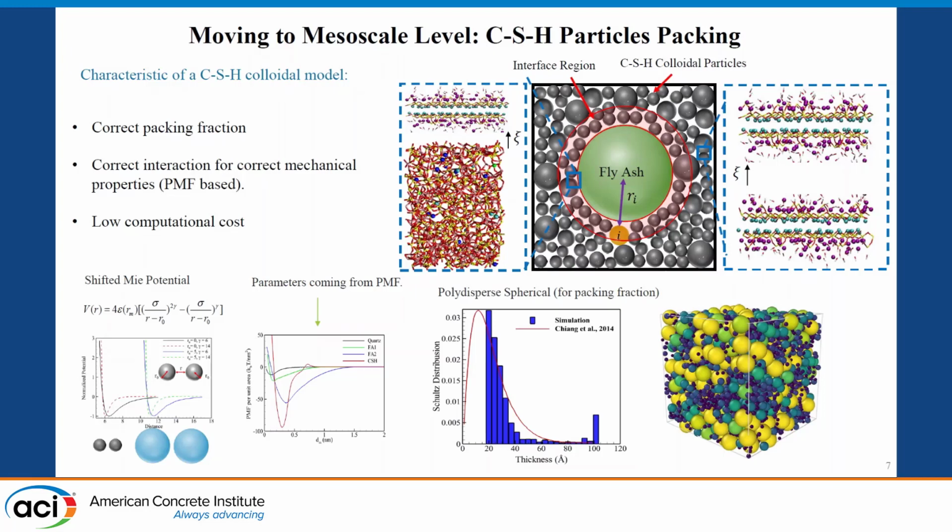And of course, we would like to be computationally efficient. So we generate those structures of spheres at various packing densities and various sizes, because we know that this distribution is not single, it's not mono. For single monodisperse spheres, you are only able to get a 74% maximum packing, and you need to employ polydisperse distributions as well.